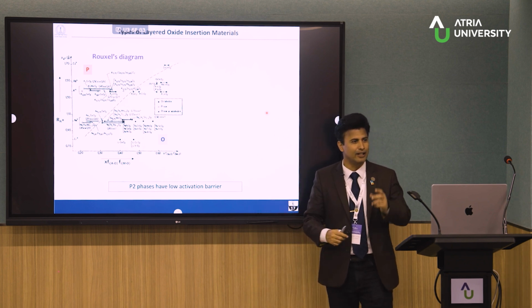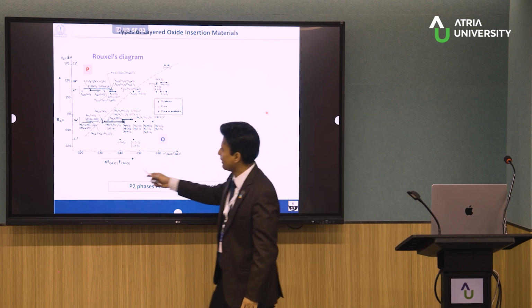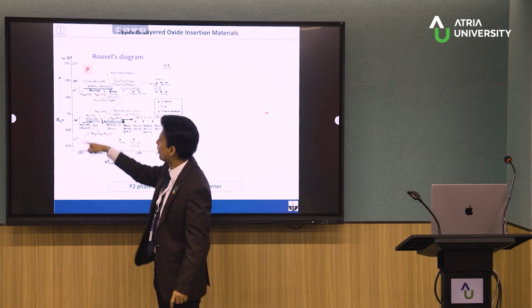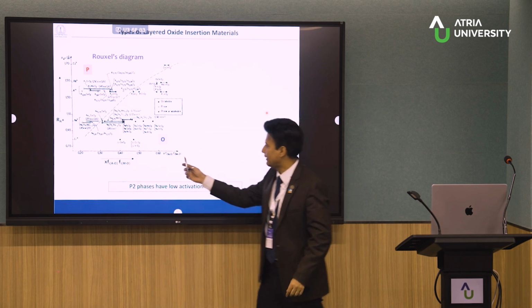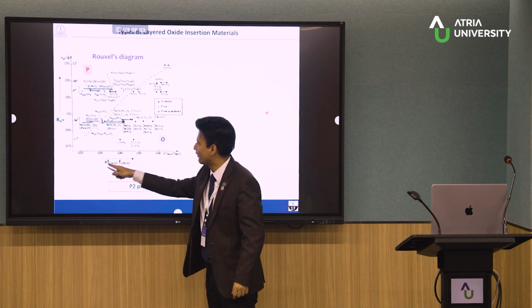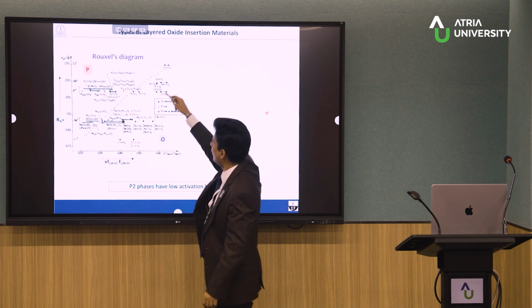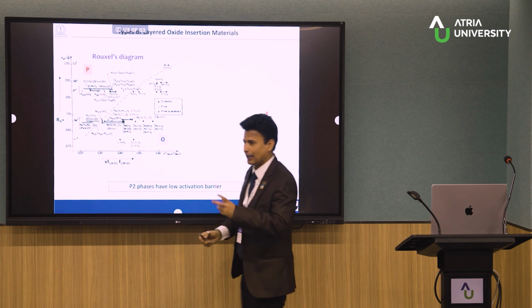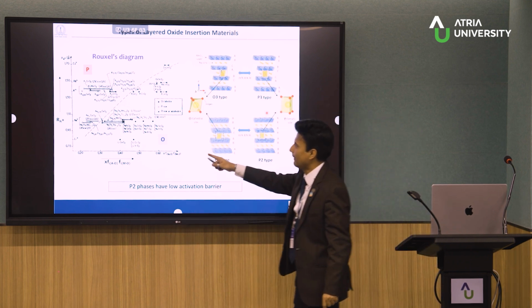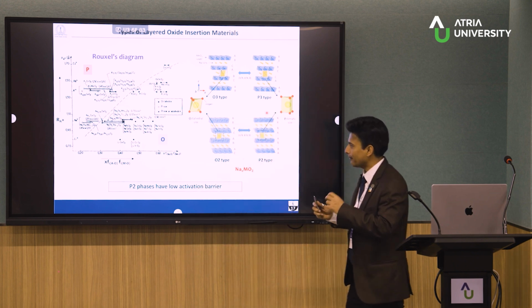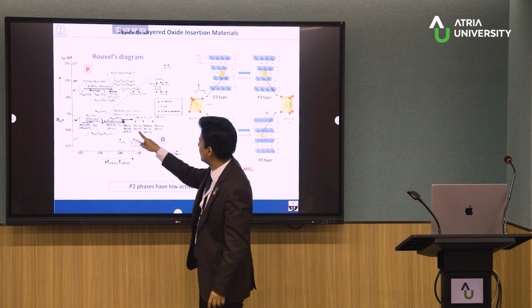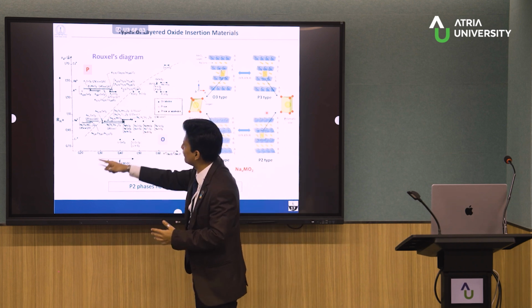Again, going back to Professor Jean Rouxel, he classified all the oxide materials into two different types, in a map like this. This is the cationic radius: lithium, sodium, potassium, rubidium, cesium, all kinds of things. Slowly it is getting bigger and bigger. And this line basically shows the electronegativity of the alkali-oxygen bond and metal-oxygen bond. There is a function. So if we put all kinds of oxide, pretty much it follows a kind of 45-degree line. Anything that goes above that has a P kind of structure, prismatic. Anything below that has an O kind of structure. So this was like a universal map, and this is true even for potassium-based oxide and so on. These are sodium-based oxides, potassium-based oxides, lithium-based oxides. Everything will follow the same thing.